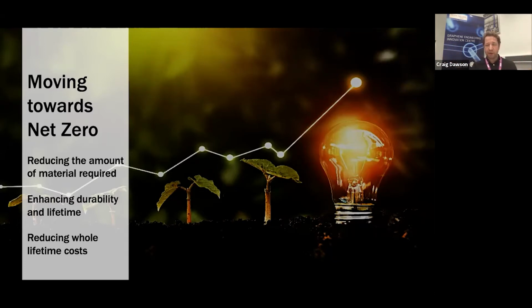By adding small amounts of graphene to some systems, we can drastically reduce the amount of material that's required for a specific task. Alongside that, graphene has unbelievable barrier properties, so nothing can go through graphene. Molecularly, even helium can't go through. So we can impose those properties onto a system as well. We can enhance the durability, and because we're only adding small amounts, it allows certain amounts of re-engineering to be done. So we can take material out, and we can change systems up if we're being really disruptive. And in some cases, we can reduce the whole lifetime cost of an application, as well as enhancing the sustainability of that application.